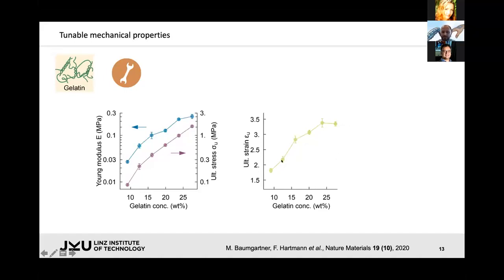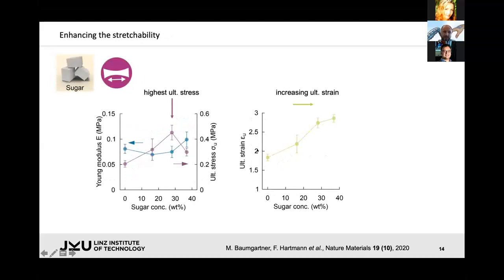This is quite neat. But since this is relatively commonly achieved, if we want to go beyond this and have high ultimate stress and high ultimate strain, then typically by adding certain sugars as a co-solvent, you can modulate how this gelatin network interacts with itself and how these physical crosslinks are formed.